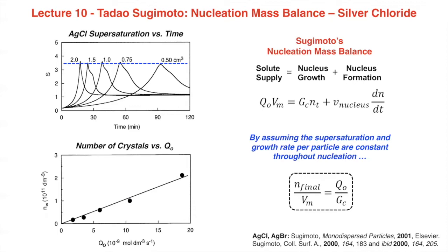And any new solutes that are generated by the solute supply at that point do not raise the concentration in solution, but instead cause nucleation, because nucleation turns on so incredibly steeply, you can't push the concentration any higher, and instead all monomers formed deposit on existing crystals.